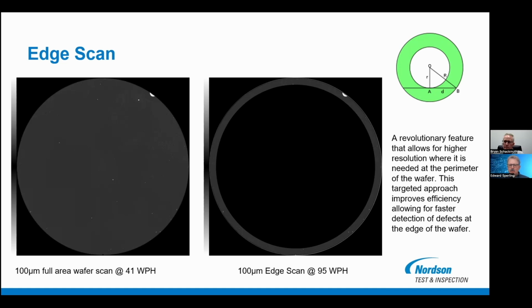So if you think about this whole hierarchy of inspection, where you go from optical all the way up to X-ray, where does this one fit in? Yeah, so it's complementary, I would say. Optical is going to be anything on the surface that would be visible. You're not looking in the sample. X-ray is really geared towards density changes, like the solder balls and metal traces. And then acoustic is very complementary with X-ray. We're able to see more of the cracks and delamination. So I would say most customers are still going to be doing all three of those inspection types. As we start getting into things like backside power delivery, which is happening on the wafer,